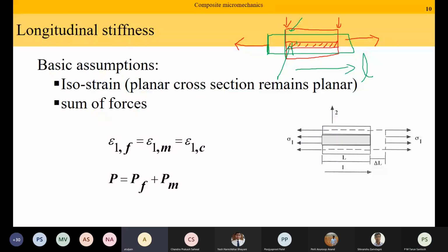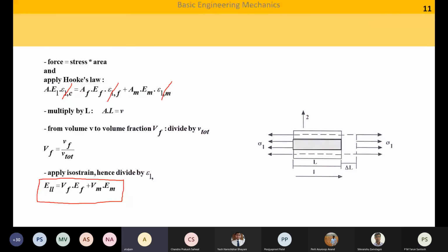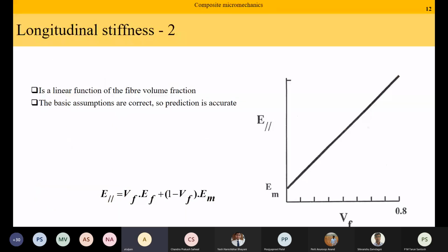Okay. Based on this isostrain assumption, you can calculate the effective properties, which says that it is basically a simple rule of mixtures. If I know the volume fraction of the fiber, the volume fraction of the matrix, and the modulus of the fiber and the matrix, I can calculate the apparent or effective modulus of the composite in the longitudinal direction. And this formula also tells me as I increase the amount of fibers, the modulus typically is going to increase in a very linear fashion. More fibers, more modulus. Okay.